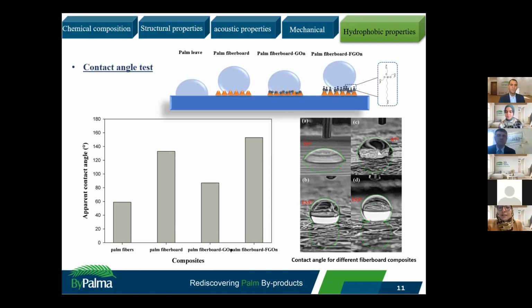However, the decrease in contact angle, which is shown in figure C on the left, of course depends on the hydrophilic oxygen-containing functional groups on the graphene oxide surface. So the addition of functionalized graphene oxide led to an increase in the water contact angle value to 153 degrees. I said degrees Celsius, it's just degrees. That can be explained by the hydrophobic alkyl chain of silane molecules grafted on the graphene oxide, and then by the high amount of functionalized graphene oxide nanosheets in the palm fiberboard composites.